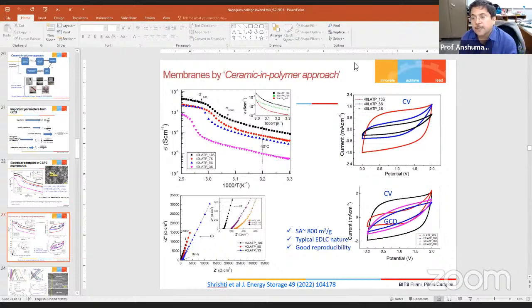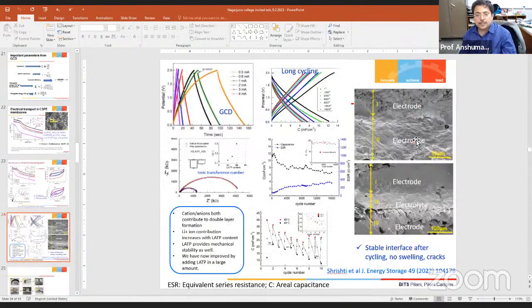And then you can compare how the other compositions were making the supercapacitor effect. And then we find that, for an optimized composition where the salt content in the electrolyte and the NASICON content in the electrolyte is good, then that was leading to a large value of capacitance. Then the continuous charging discharging profiles up to 16,000 cycles could be worked out. And we could see what the interface is after the cycling. The solid-solid interface after the cycling is seen here, and it's quite intact after the cycling.